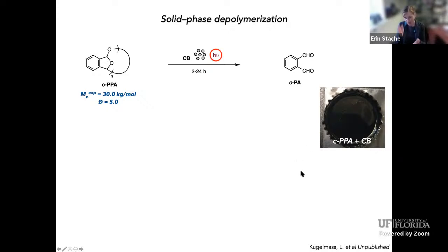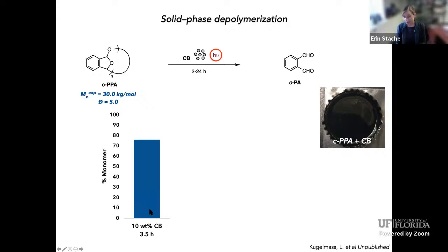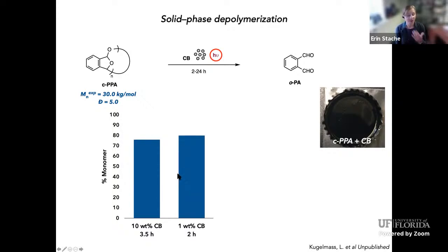And so usually what she does is she cuts off a little piece of film and then sticks it in a vial in front of the light. And with 10 weight % carbon black after 3.5 hours, it's pretty much depolymerized back to monomer very cleanly. We just see polymer and monomer in the NMR, about 75%. Interestingly, as she decreases the amount of carbon black to just 1 weight %, it's actually even more efficient.